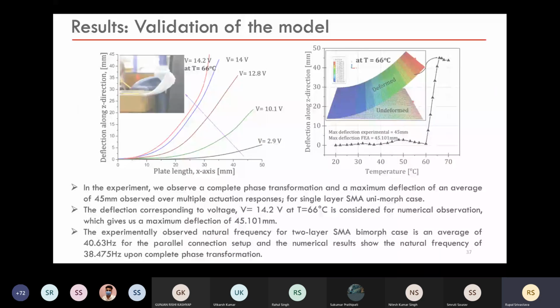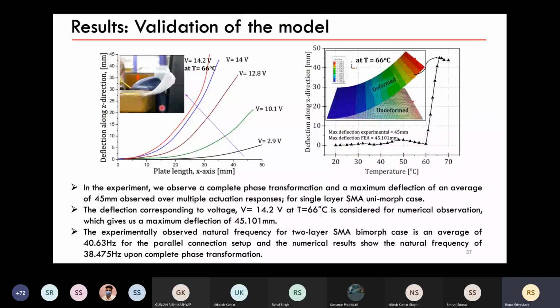So in our experimental model, this is when only one layer of shape memory alloy is reinforced, as I talked about previously. We have a maximum of 45 mm of bending. And when I did it using FEM, I get 45.101 mm of bending. So here we have an average of 45, that's why I took it as 45 mm. And here we have 45.101 mm. And this T equal to 66 degrees Celsius is where I get the maximum amount of bending, which means that our shape memory alloys are at their austenite finish temperature, so they are in their austenite phase. Once we have validated the model, we build our model on different types of auxetic structures, which I explained. Here there are 2 layers of shape memory alloy wires.